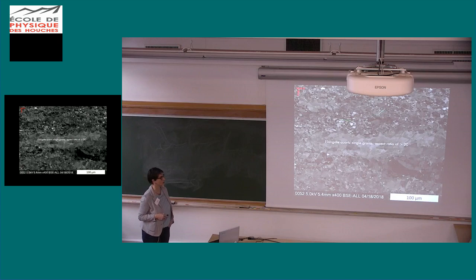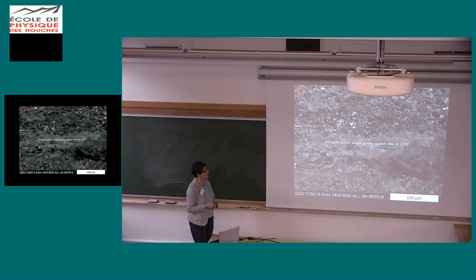We see strongly increased porosity in the areas where we have the shear bands. And we see these strongly elongate quartz grains. They have a really amazing shape preferred orientation and crystallographically controlled preferred orientation. The aspect ratio is sometimes even up to 20 or so. So amazingly long and big quartz crystals that show a whole bunch of internal deformation structures. But our fine-grained area is very different from that by the high porosity that is highlighted here.